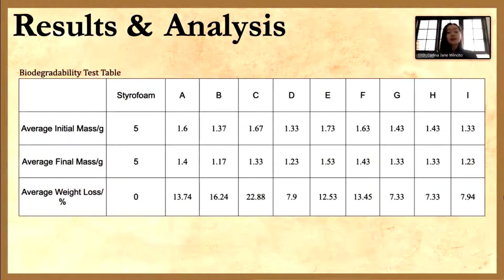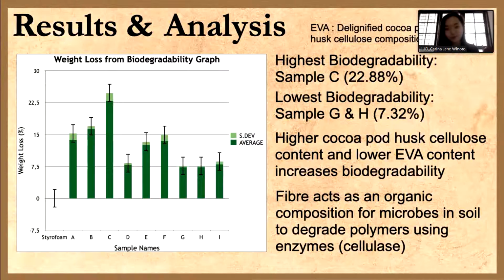Lastly, the results of the biodegradability test, its weight loss, are as follows. When such results are placed in a bar graph, you may notice that the highest biodegradability was found within sample C at 22.88%, while the lowest was found equally in samples G and H at 7.32%. This alone shows that with higher cocoa pod husk cellulose content, and especially with the addition of lower EVA composition, biodegradability is promoted to increase weight loss.